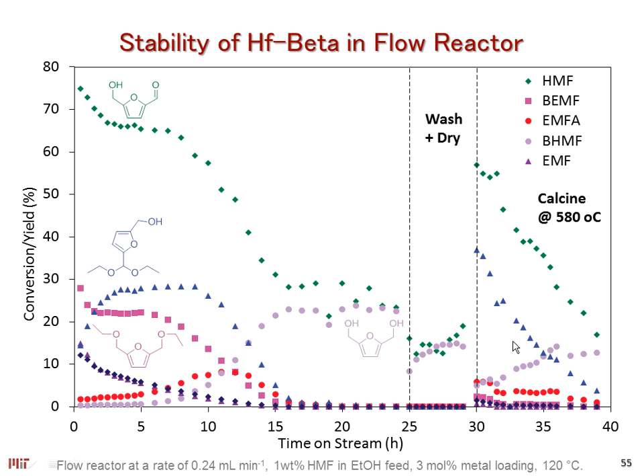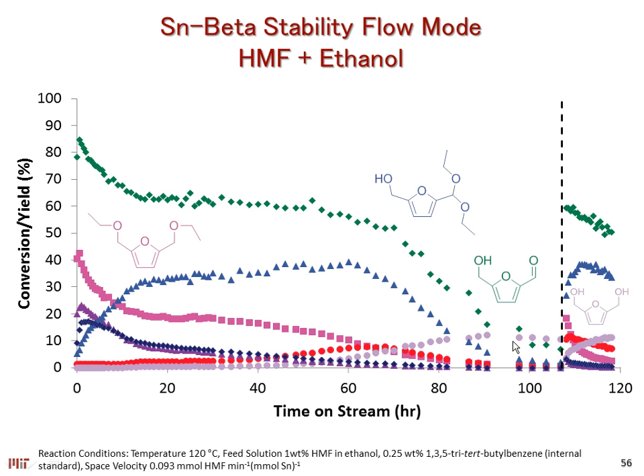and after this second deactivation step, we actually changed the product distribution quite drastically, and instead of producing our etherification products, we continuously produce our dialcohol products over here. If we switch to our tin catalyst, we see that even though it's a little bit slower for the etherification of HMF with ethanol, it's a little bit more stable, still producing, though, quite a bit of acetal byproducts and deactivating very slowly over here with respect to the diether.